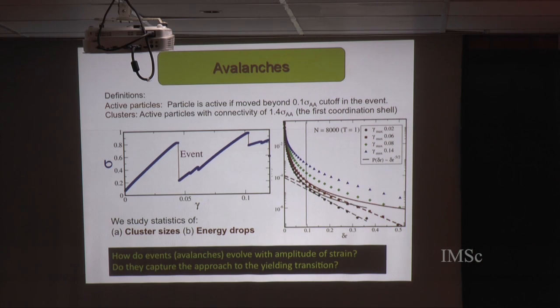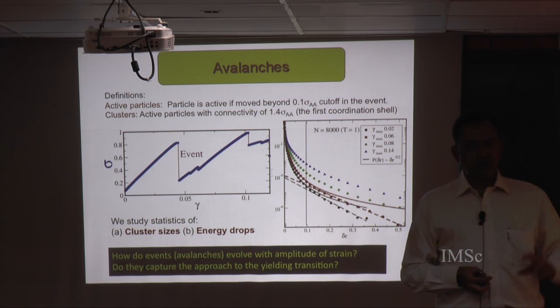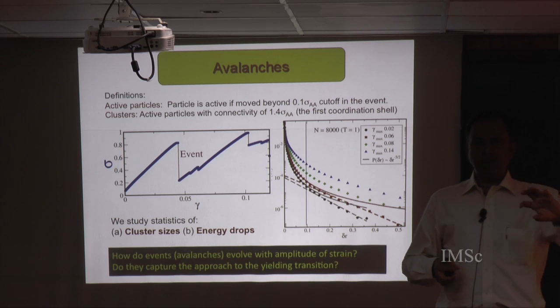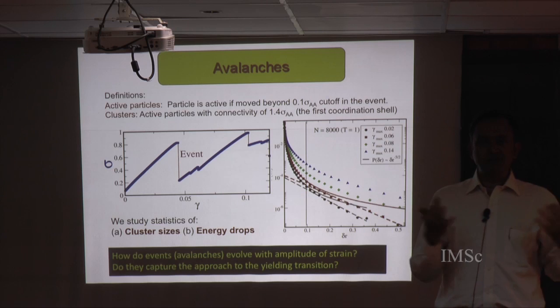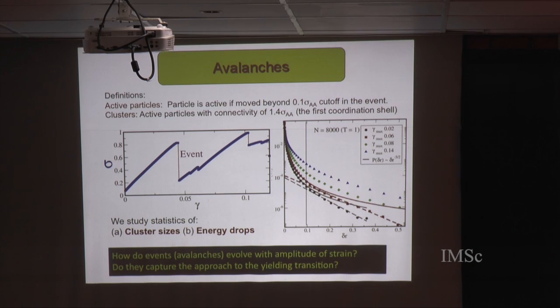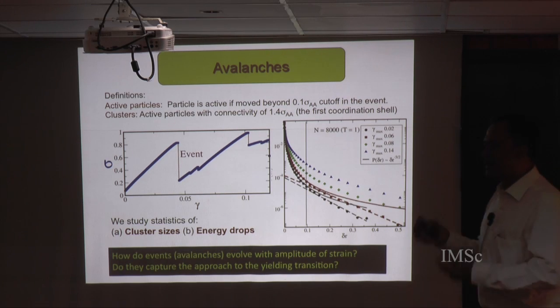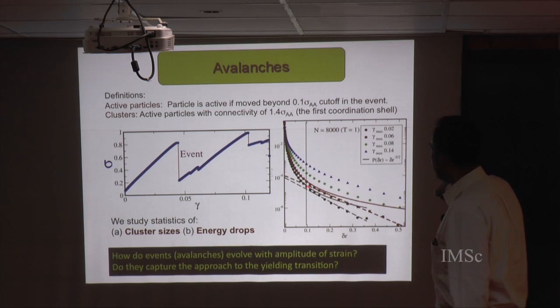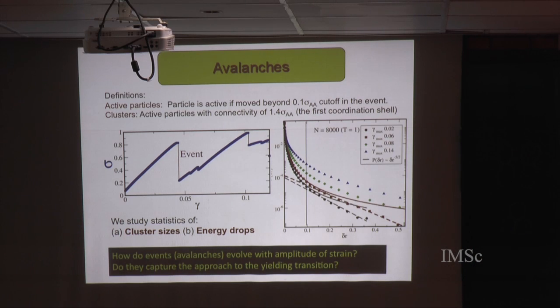One can understand this by saying that if I had, like in the Eshelby picture, a local plastic deformation, it would induce linear elastic displacements of particles farther away, and these linear elastic displacements can explain the power law part. So what one would really like to focus on are the particles sitting in the exponential tail of the distribution. The problem is it's not a very sharp separation to make.